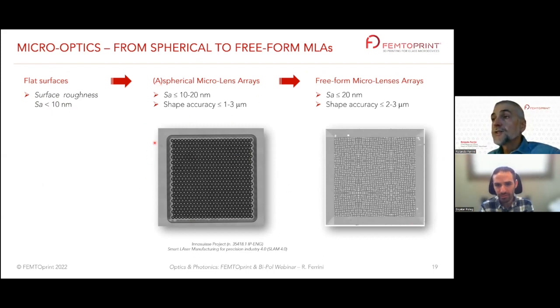If you start corrugating the surface, if, for example, we have a microlens array, then we have to find a compromise between how much we can decrease the roughness and how much we can modify the shape with the post-process. Here is the trade-off. Usually we have an average roughness between 10 and 20 nanometers and a shape accuracy which is between 1 and 3 microns. If we go to fully free-form microlens arrays with high sags, then we have the trade-off with average roughness in the order of 20 nanometers and shape accuracy 2-3 microns. That's the rule of thumb.